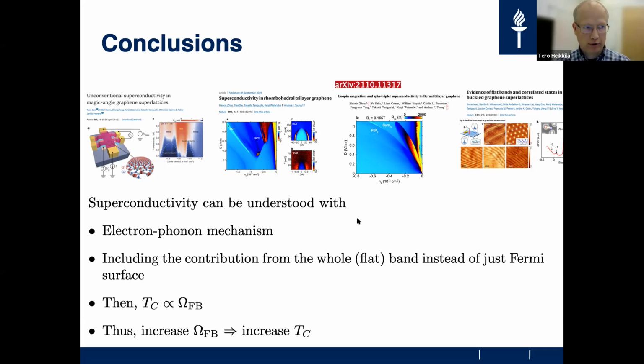But in order to understand it quantitatively, you need to include the contribution from the whole flat band instead of just the Fermi surface. So the nature of superconductivity in that sense is somewhat unconventional. And in this case, the TC is proportional to the area of the flat band. And in order to increase the TC, we would like to increase the flat band area in some ways.